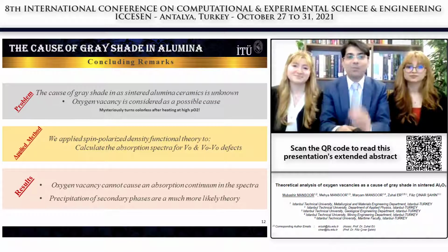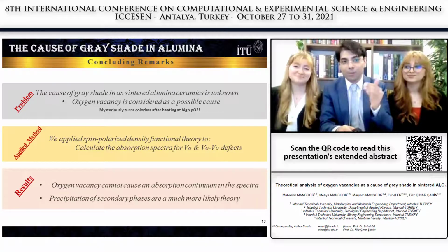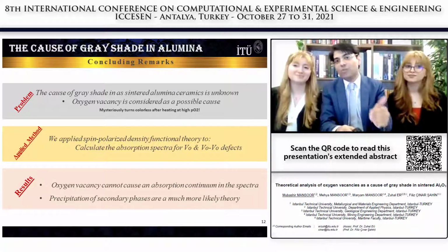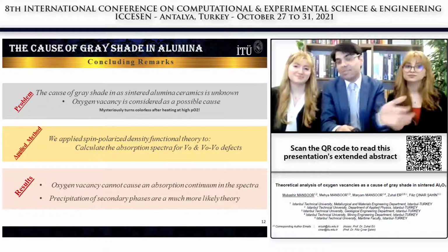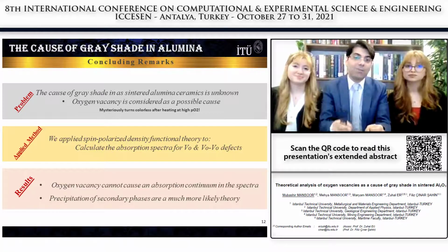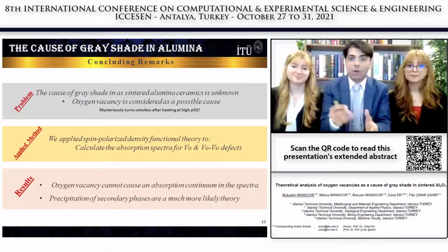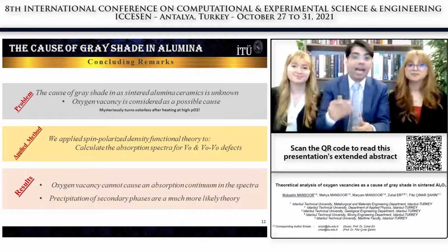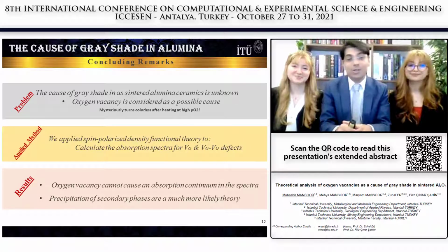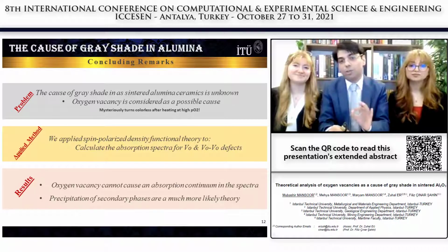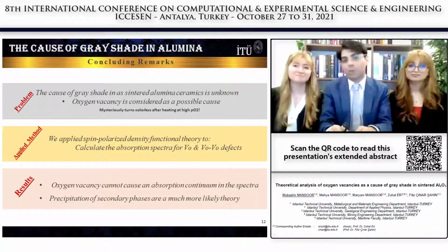So to conclude, just a quick recap. The problem that we tackled was to find if oxygen vacancy can cause a gray shade in as-sintered alumina ceramics. We applied spin polarized density functional theory to calculate the band structure and optical response function of the oxygen vacancy and di-vacancy defects. And we found out that these defects are definitely not a possible cause for the gray shade. And also, we anticipate that secondary phases, such as iron, are a much more likely cause, which makes it very crucial to study these ceramics under high resolution TEM to be absolutely sure of what's going on.